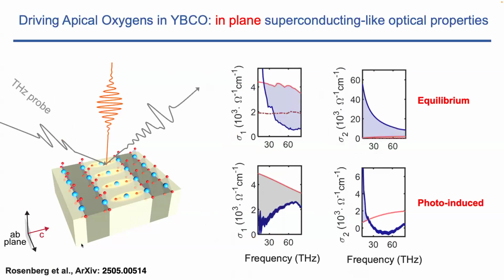Now, recently, we've looked at results in plane. This is what you see in equilibrium. You go from this state to the divergence of sigma 2, and you go from this state to the gap opened in the superconducting state. When you pump it, you generate something that looks like the divergent sigma 2, although it's smaller, and you open the gap.